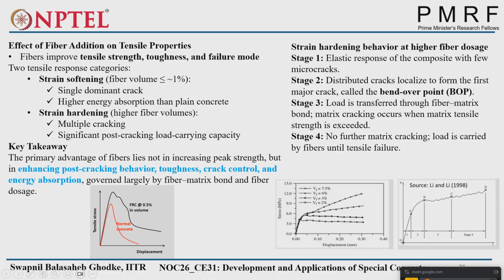So whatever fibers are available in between that first crack will start to resist the crack widening, and because of that, a small amount of micro cracks will increase, or multiple cracking will happen in the area between B and C. Then stage 4: no further matrix cracking happens and load is carried only by fibers until tensile failure. What is tensile failure? It means the fiber itself will break down.